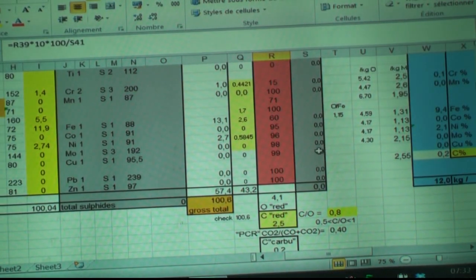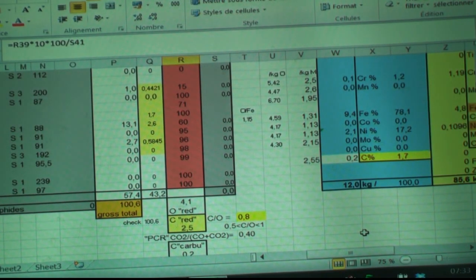When you calculate the coke, you will calculate the coke. And of course, after designing the installation, you must put a margin. You must say coke can be more sometimes. But what the customer says to you is, I want a metal with 20% nickel at least, or 22. The coke you calculate, or maybe he gives something typical. This is the Fe yield. You see, to have 20% nickel. You mean the Fe and the nickel? I think it is better to discuss after we studied this.